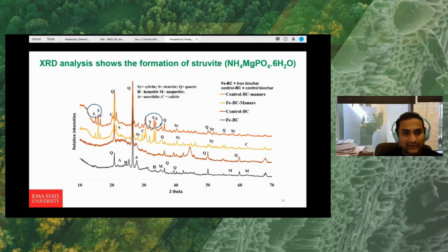So in both the control biochar manure and iron biochar manure, we have found a struvite formation, an ammonium magnesium mineral with the phosphate, and we attribute that this is the main reason that ammonia and phosphate are getting stabilized in the biochar system. Swine manure has a huge amount of magnesium and calcium itself, so the magnesium is coming from the swine manure.